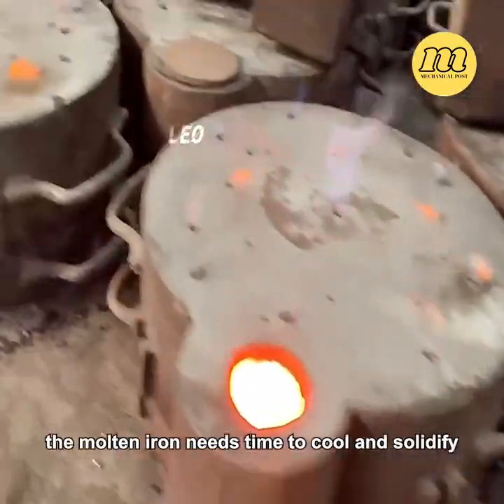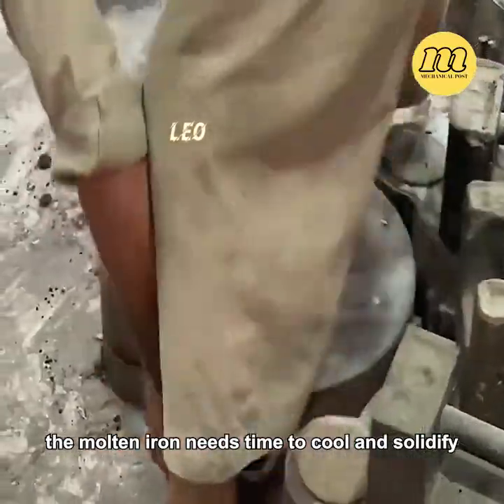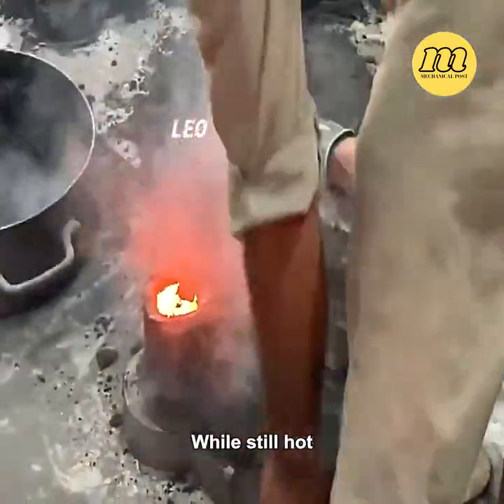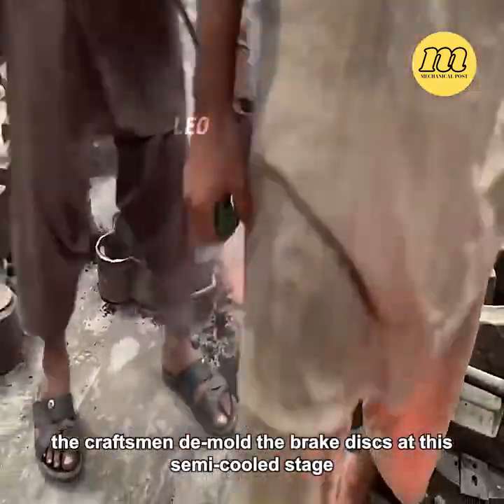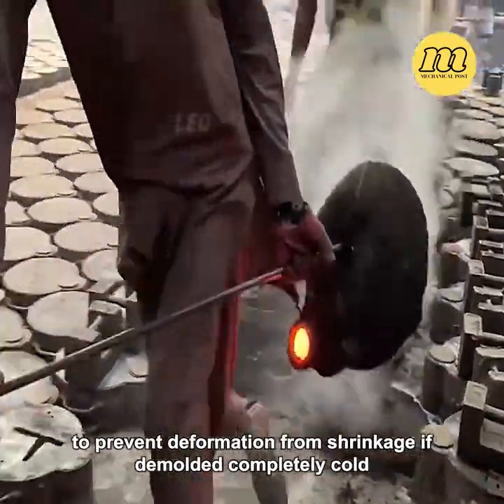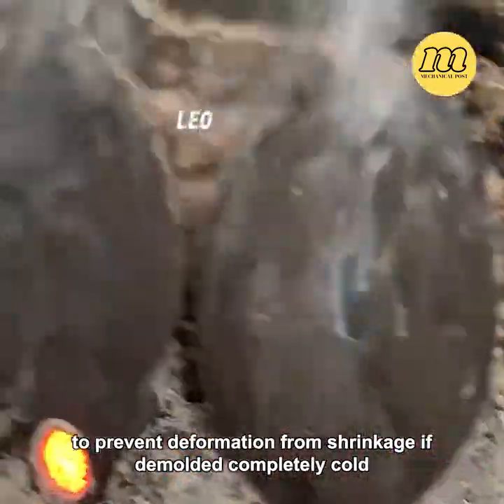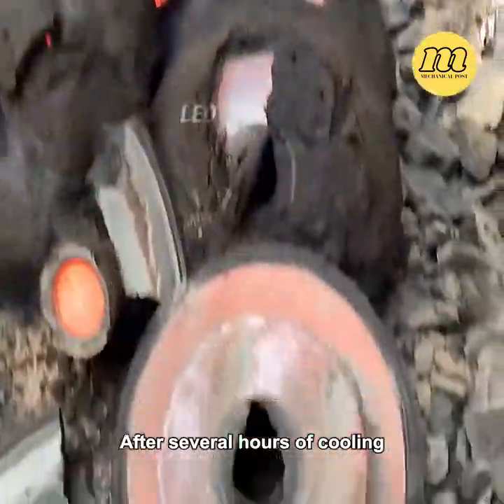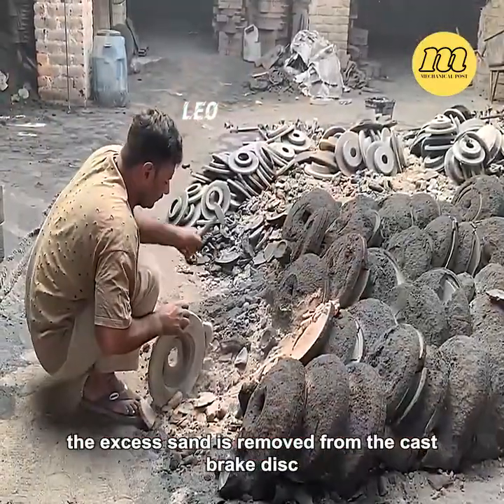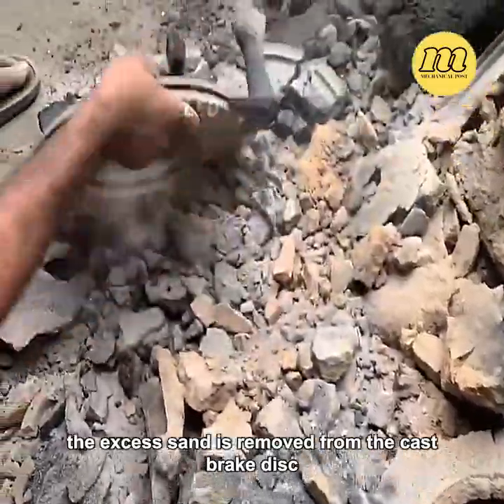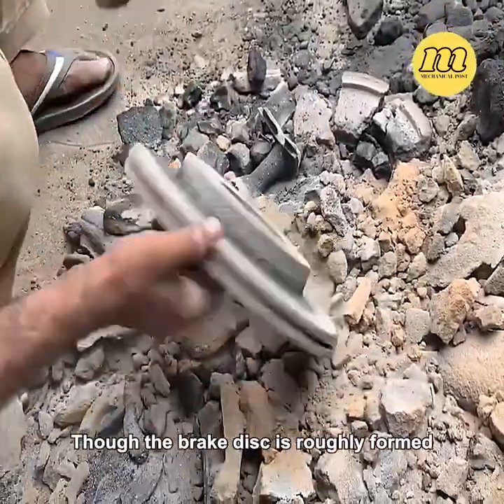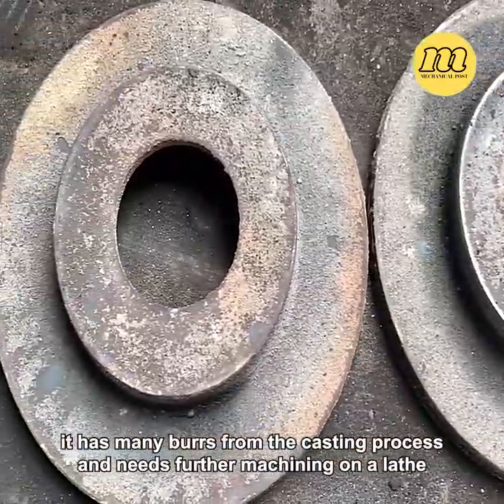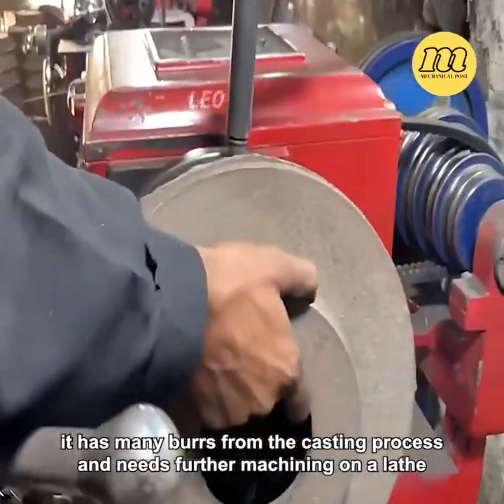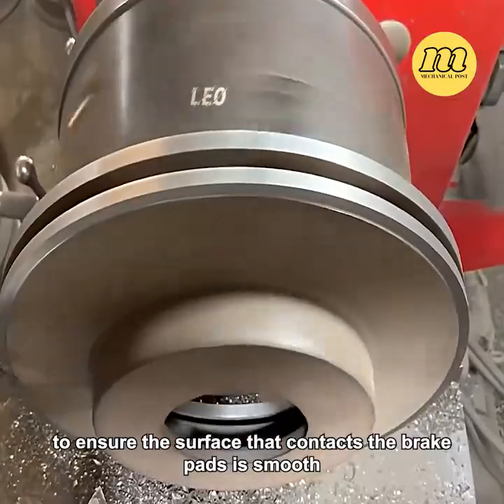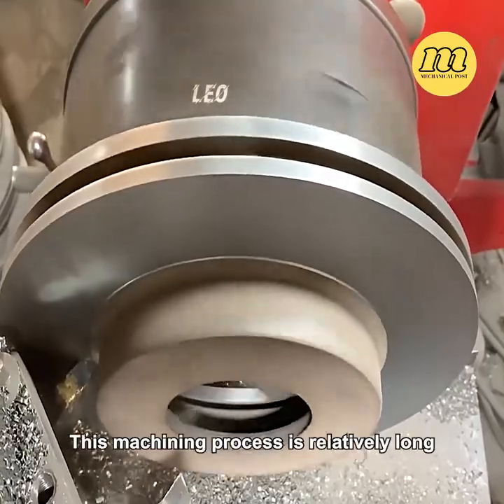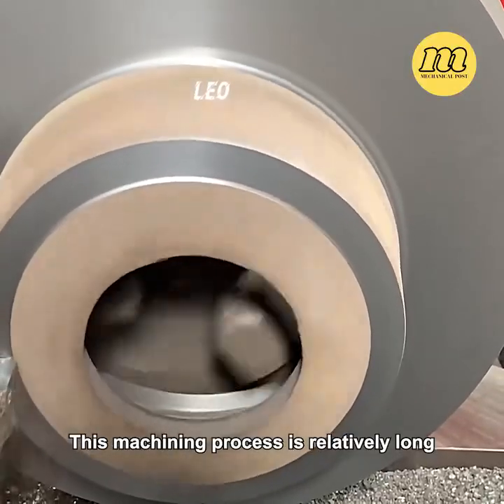After casting, the molten iron needs time to cool and solidify. While still hot, the craftsmen demold the brake discs at this semi-cooled stage to prevent deformation from shrinkage if demolded completely cold. After several hours of cooling, the excess sand is removed from the cast brake disc. Though the brake disc is roughly formed, it has many burrs from the casting process and needs further machining on a lathe to ensure the surface that contacts the brake pads is smooth. This machining process is relatively long.